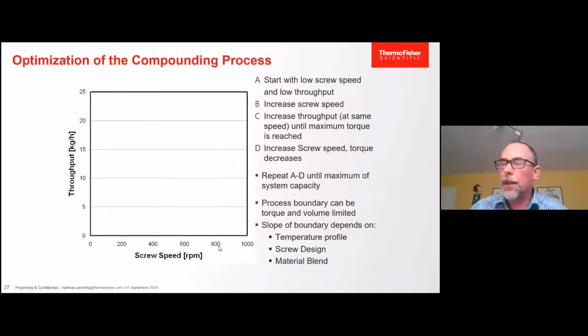When we go over and see a nice diagram of how we will develop a twin screw process with these extruders, there is one mistake many customers actually make because they're used to single screw extruders. A single screw extruder is operated in a way that when you increase the screw speed, the output will increase. So the single screw extruder will normally take all the material it can get from the hopper. In this case, for a twin screw, it is different. A twin screw always uses controlled feeding.